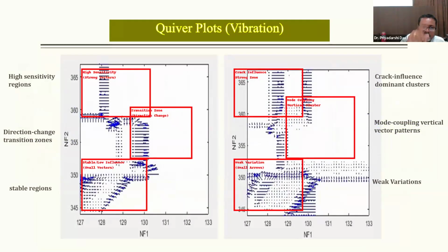We can see from the three highlighted zones: the high sensitive region, direction change, transition zone, or stable region. From 345 to 350 Hertz natural frequency, we can say that this is a stable region. After 350 Hertz, the direction change, transition zones are there. That means severe cracks have been experienced. And after 360 Hertz, we can see the distorted figure that enables the reader to identify that there is a severity of the crack. That means the depth of the crack is increasing or the location of the crack is shifting.